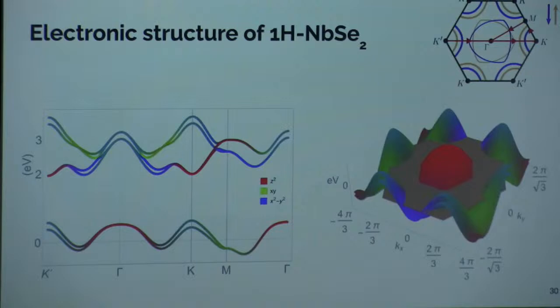In the special clean case, we can Fourier transform everything to momentum space and then obtain the bands, the electronic structure. Since there are 3 orbitals, there will be 3 bands, but because of spin-orbit coupling, these are split into 6. If you want to study superconductivity, all that matters are the bands crossing the Fermi level.